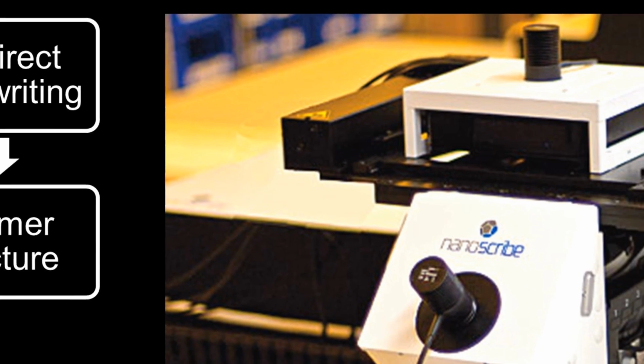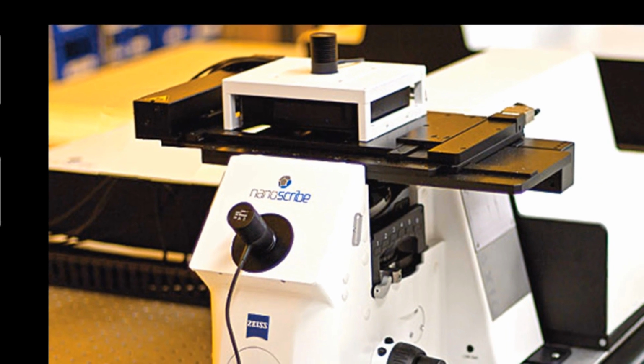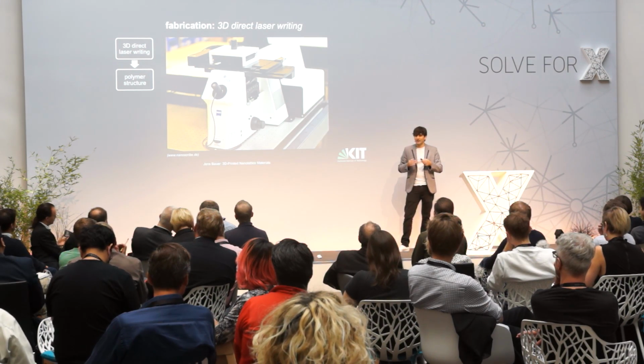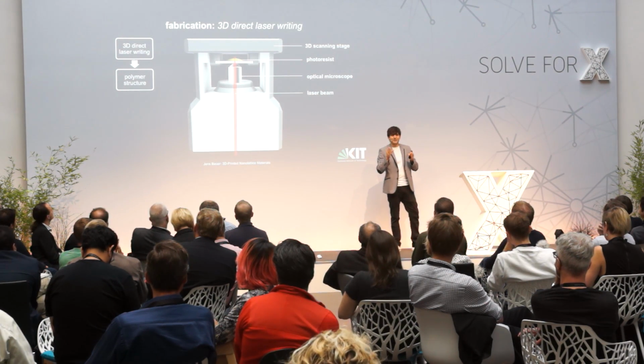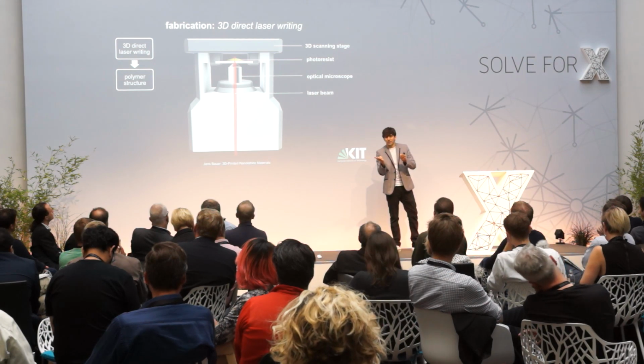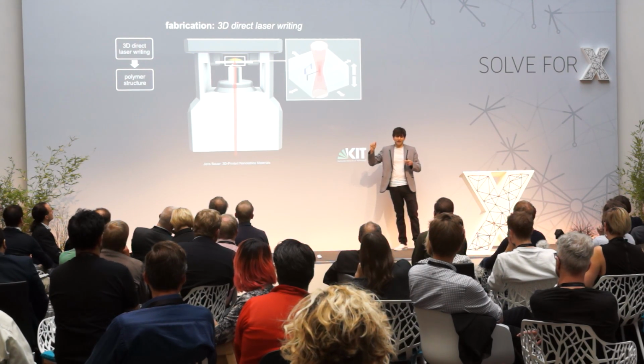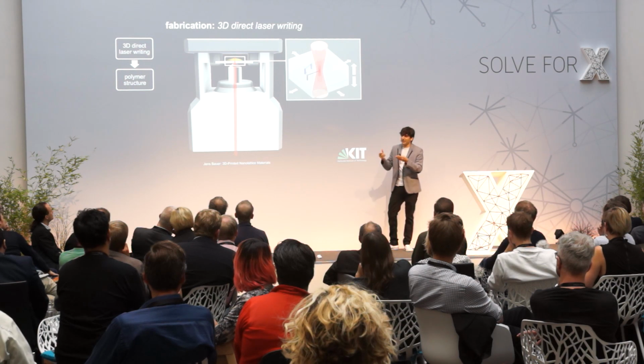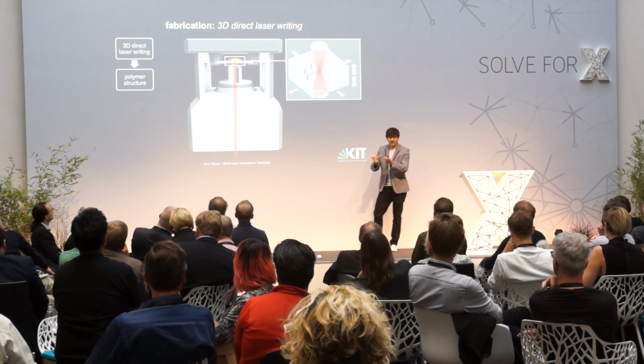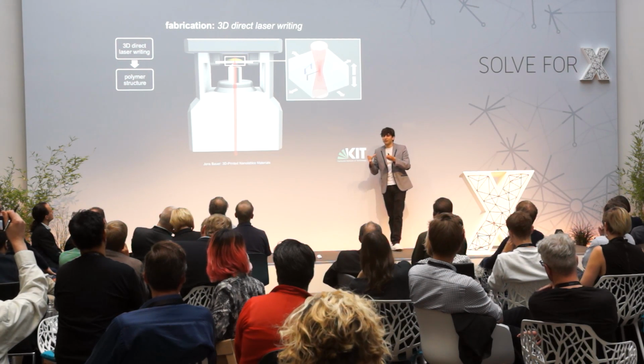We manufacture such nanolattices by means of 3D direct laser writing. That is a two-photon lithography process, which is capable to create three-dimensional structures with a sub-micrometer resolution. Therefore, a pulsed laser beam is focused on a sample holder with a liquid photoresist on it, which is UV sensitive, by an optical microscope, as illustrated here. Now, at the very focal spot of the laser light, the photoresist polymerizes, means solidifies. Now, by moving the sample stage around, and by scanning that laser beam, we can actually build three-dimensional nanostructures.